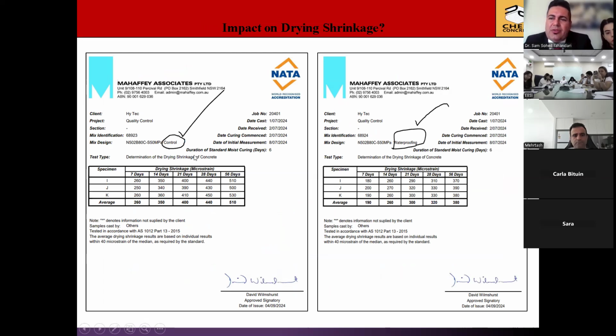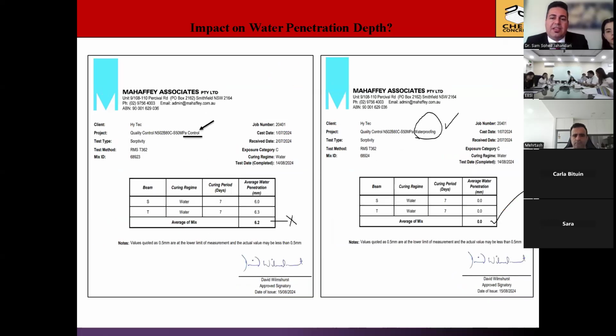Usually drying shrinkage is one of the major issues for concrete cracks, especially at the early ages of curing. For example, here we can see our product has significantly decreased the drying shrinkage of concrete. After 56 days, the drying shrinkage was 510 for control concrete, and in the case of concrete with our product, it was 380. So these are all very positive results, which show that the admixture not only has very good waterproofing and durability performance, it also has other valuable benefits as well.